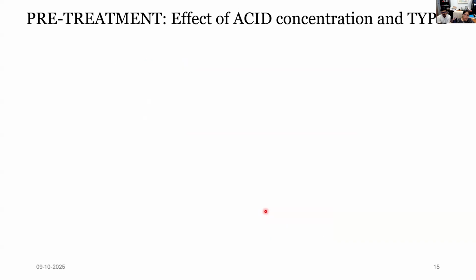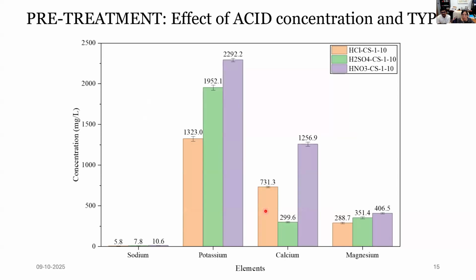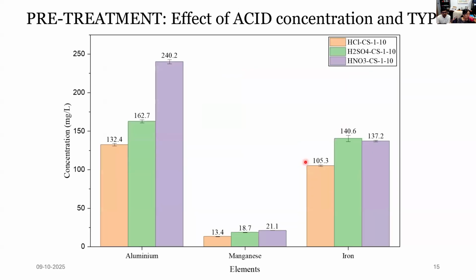Next, coming to the effect of different types of acid. Here we can see for all the corn stover ashes, we washed the ash with hydrochloric acid, sulfuric acid, and nitric acid at 1 normality at a similar acid to ash ratio. So here we can understand that acid becomes very selective in removing particular impurities from the system. For example, in this figure, we could see treatment with nitric acid enhances the potassium release and calcium release a lot better. And when it goes to heavy metals, we can see that when we use 1 normality nitric acid, we had a higher release of aluminum from the system compared to hydrochloric acid and sulfuric acid.